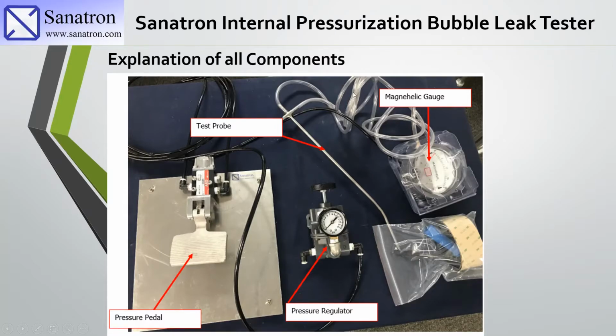And then finally, this system also has a magnehelic gauge, meaning that it detects a pressure difference between the samples. So there are 2 lines here. One is pressure in and the other one is pressure differential, meaning that if you have your probe inserted into your specimen and your pedal is pressed and you are seeing a pressure differential, there are 2 reasons for that. First of all, your sample is inflating, or second of all, there is a leak because there is a pressure drop, since the pressure coming in is not the same as the pressure inside the pouch.